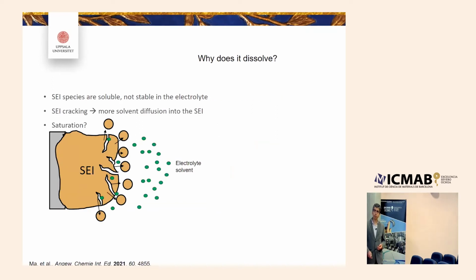The problem with SEI is that you may form cracks, allowing solvent diffusion through it, which leads to more irreversible capacity, and that's why we want it to be very, very stable.